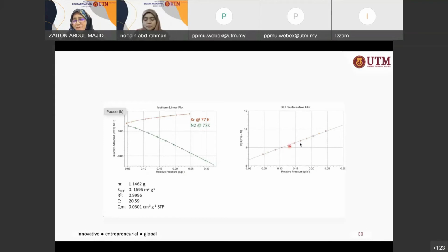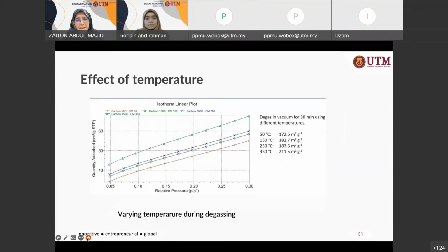Otherwise, if you get a straight line with the right correlation coefficient, 0.9999 or 0.999, preferably 0.999. But in this particular case, since this is the best, at least you get a linear range, then it's okay. Okay. Now, what is the effect of temperature on the degas?